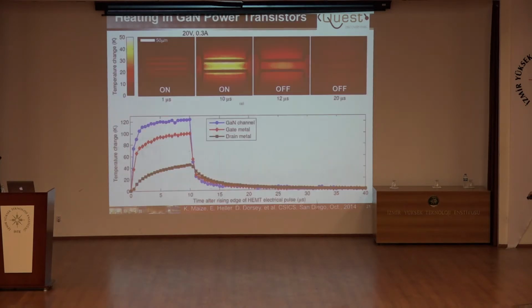One of the things you realize is that temperatures change on the time scale of a few microseconds, but it's very heterogeneous. The channel has 120-degree heating, while the drain, which is only a few microns away, is only 40 degrees. There is a huge temperature gradient inside the device, and this is a major reliability issue, and that's one of the reasons people need to characterize this.